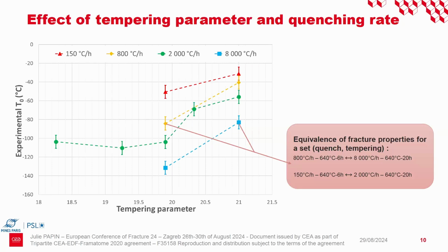Another thing that the graph reveals is that we observe equivalence of fracture properties for a set of quench and tempering conditions. For instance, for the 800 degrees per hour quenching rate, followed by tempering at 640 degrees for 6 hours, we have the same T0 as for the material quenched at 8,000 degrees per hour, then followed by a tempering at 640 degrees for 20 hours. And this is quite the same for this point.